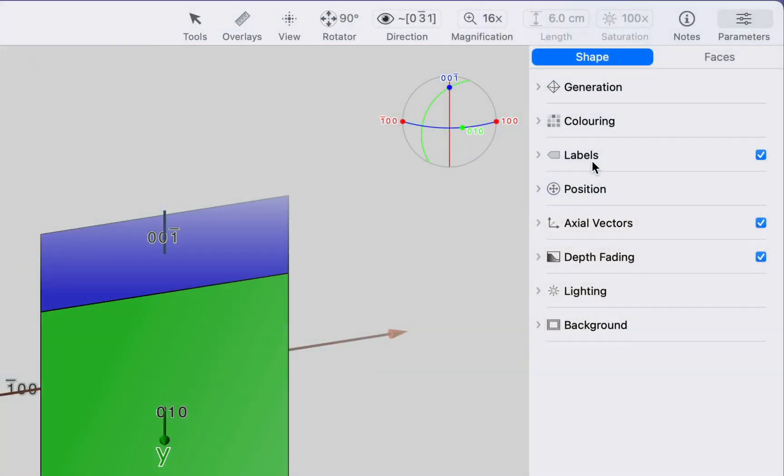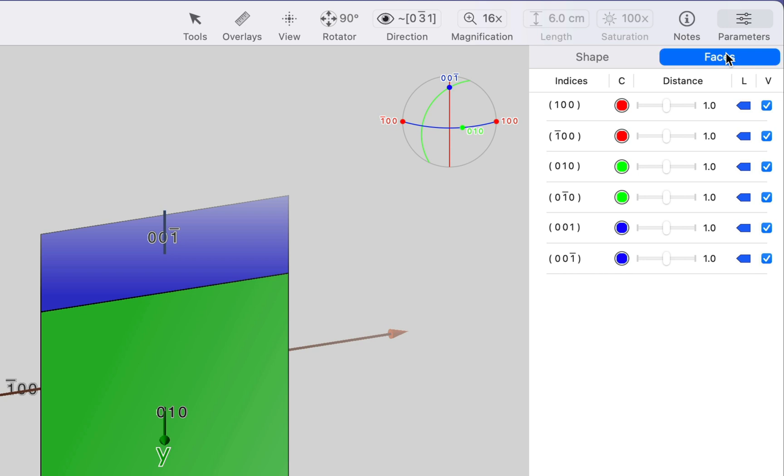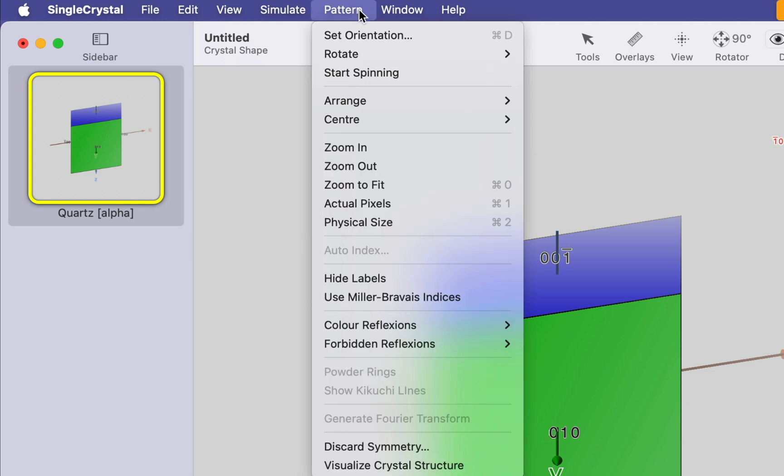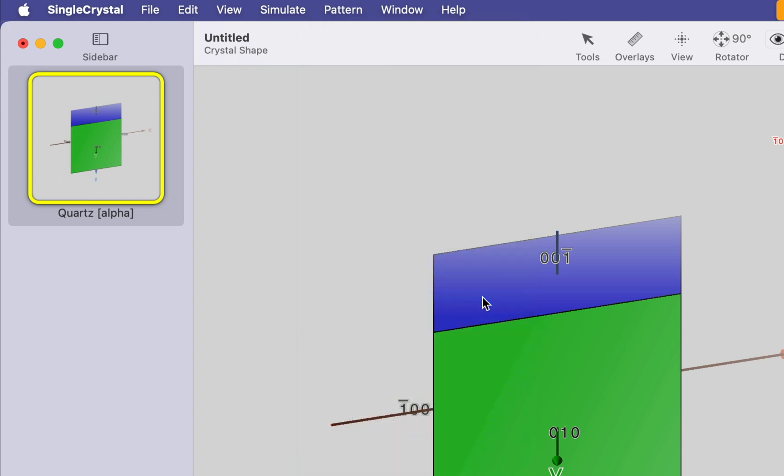Now, quartz has two main sets of faces set parallel to 100 and a set parallel to 101. And we'll add these and their symmetry relationships. To do that, we need to go to the faces inspector. And here you can see we have a default set of faces displayed. These aren't the ones that we want. We're going to edit those. Quartz is trigonal in this case or hexagonal at high temperatures. So we're going to change these three index displays to four index. And we do that by specifying that we want to use Miller-Bravais indices.